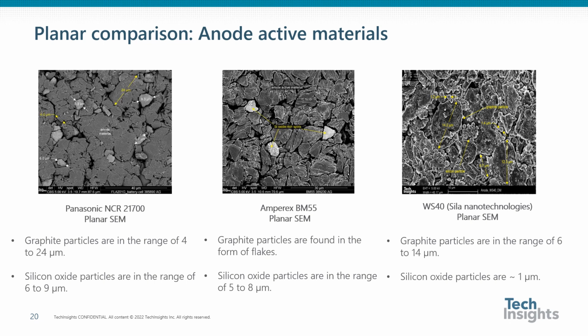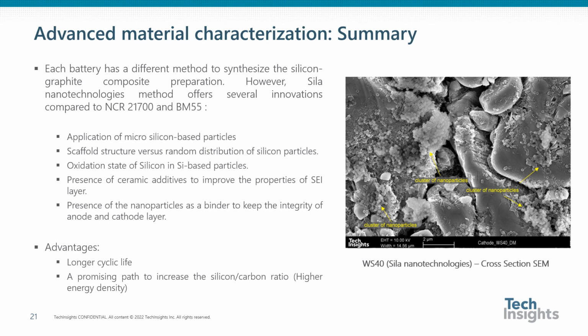With respect to WS40, we can see the spherical silicon particles confined between the graphite flakes. We perform additional material characterization on these electrodes and the results are summarized in the next slide. In detail, we performed XRD, XPS, and Raman spectroscopy on the anode of these samples.